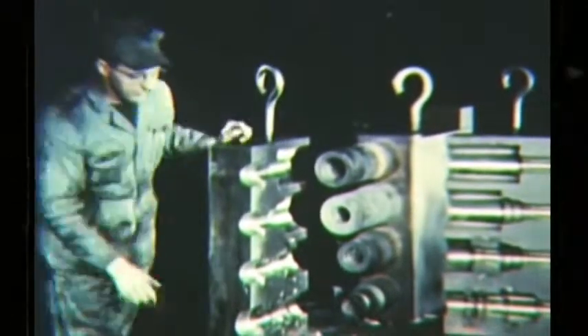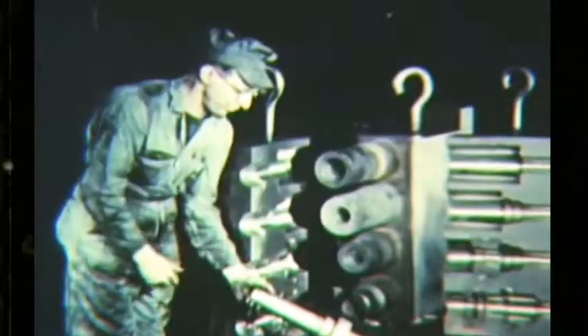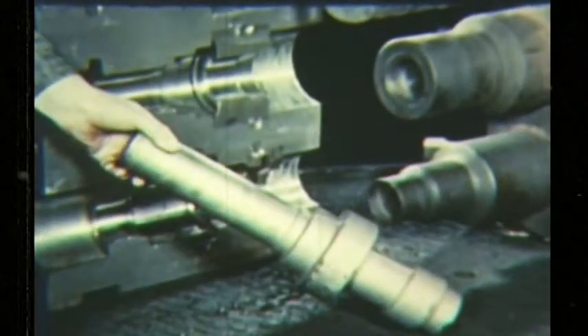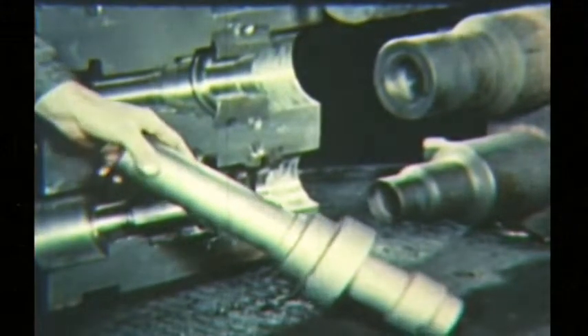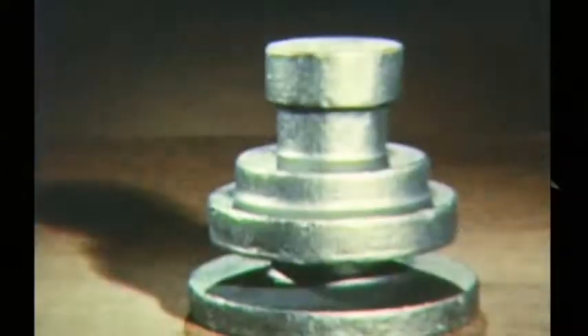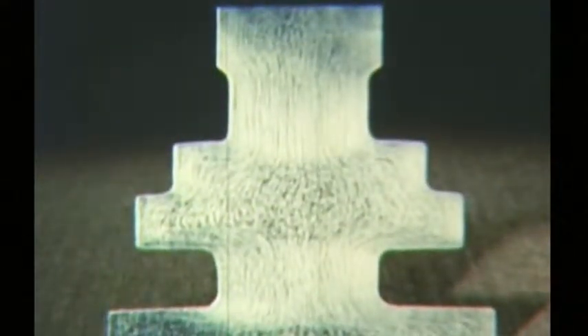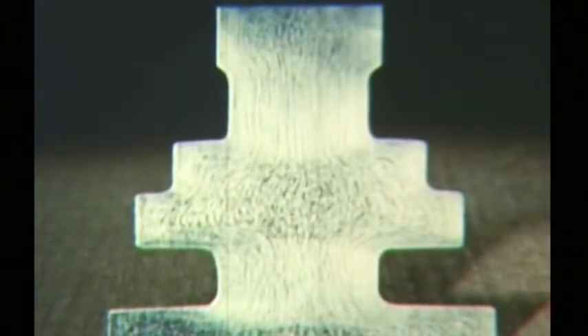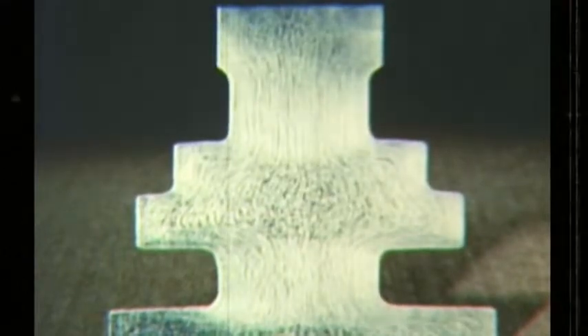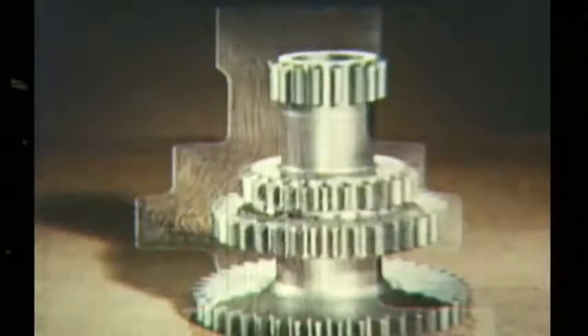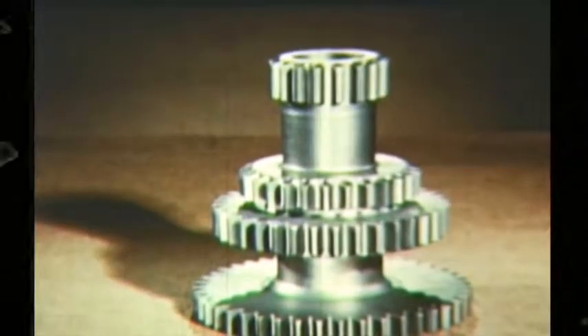To make larger or more complex parts, dies with more cavities and headers are used. This one, with 4 passes, produced this forged blank for a gear shift countershaft. This gear cluster forging was made in a similar set of dies. Cutting it in two and etching with acid shows the control of grain structure and fiber formation achieved by upset forging, which results in a finished part of maximum strength and durability.